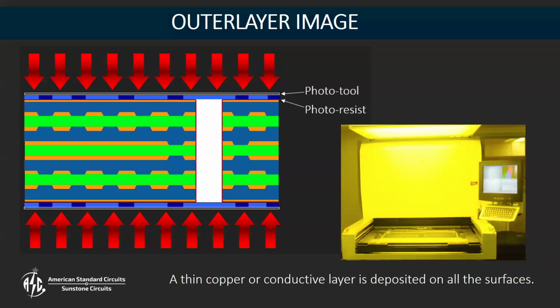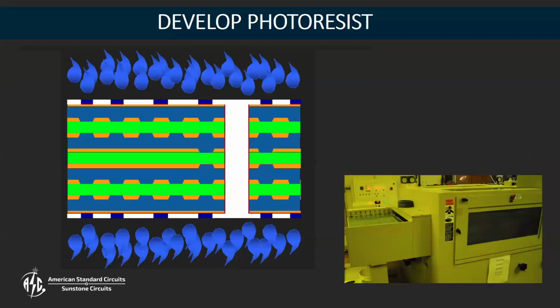So all of the traces are going to be exposed to the copper below it. All of the pads, the surface mount pads, the through hole pads, etc., are all going to be exposed at this point. And all of the copper we wish to remove to create those traces and pads, etc., is going to be covered by the photoresist that we're going to etch away later. So we use the same process, an LDI or a high intensity light source to create those traces and pads. Again, we're going to develop off the photoresist that we don't want to expose the traces that we do want to keep.